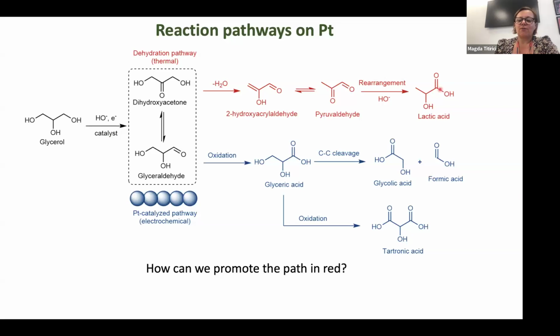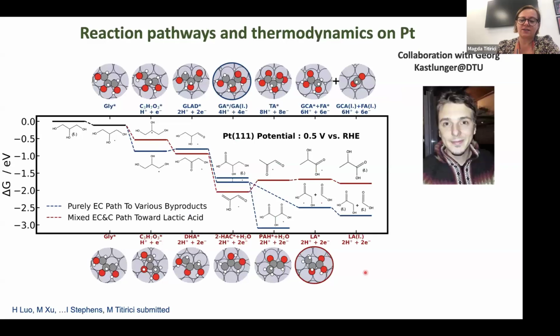Now, the trick of making lactic acid is to actually form dihydroxyacetone and stop it here, and don't form glyceraldehyde. So stop this equilibrium from forming. And once you stop this, the dihydroxyacetone is formed. You can have this chemical pathway to form 2-hydroxyacrylaldehyde, and then via a rearrangement in alkaline environment, you'll form lactic acid. So the question is, how can we actually promote the path in red?